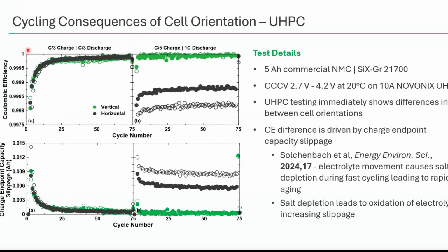This time we're not trying to remove kinetics, we're trying to see the effects of kinetics on cyclometrics. So we did C/3 cycling for only 75 cycles - about a week on UHPC - and then C/5 and 1C. Right away you can see these dramatic differences between the two, with coulombic efficiency diverging between the horizontal and vertical orientations.